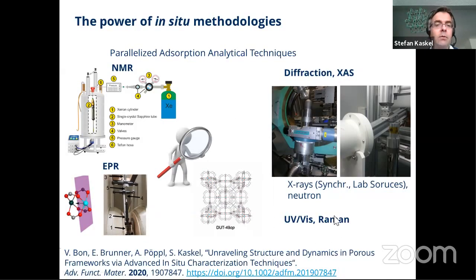I will not go into UV-Vis and Raman, but I will explain some details of what we can do with NMR spectroscopy if we connect a dosing system to a static NMR, where the sample is located in a high pressure cylinder that can be analyzed with NMR or with EPR, electron paramagnetic resonance. While the NMR looks at the gas species, carbon-13 NMR can look at CO2 and methane, the EPR can look at radicals, and many metals have paramagnetic centers in the paddle wheel or in other centers, and this can be used to follow the transitions and the structural changes in situ.